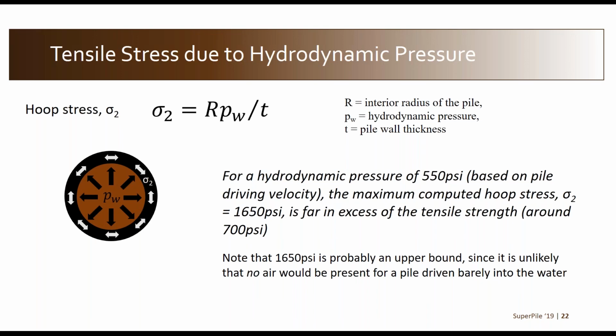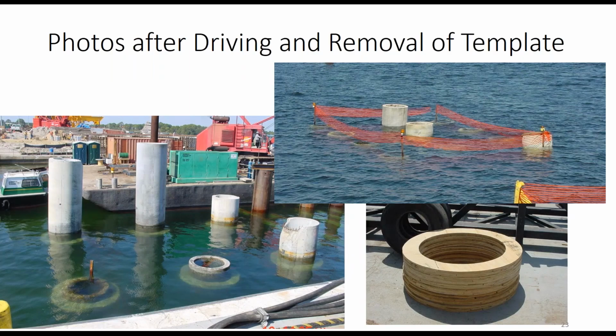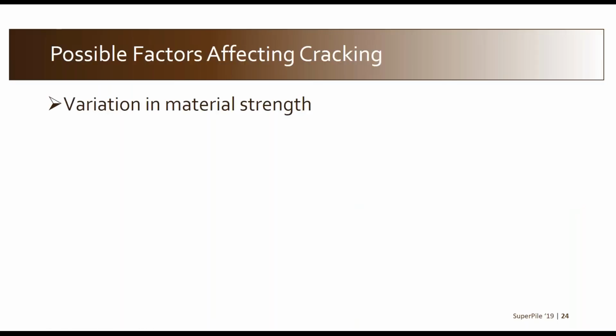Now, it's unlikely that that condition actually applied on any of these piles, even though some of them are shown here in the final condition, totally underwater. That's affected by the tides at the time of driving, although I do believe that the inset picture is one of the groups which had several of the piles damaged. So it does seem to be a factor. Also, the cushion is pictured here. That one's in pretty good shape, but as you know, the cushions wear out, and so that influences the relative stresses that an individual pile experiences depending on the condition of the cushion when they started and ended driving.